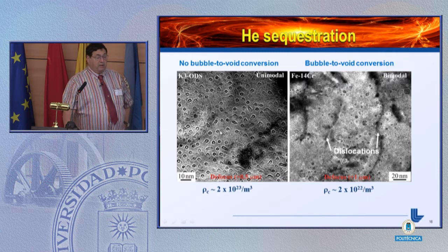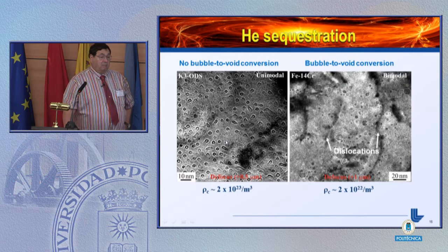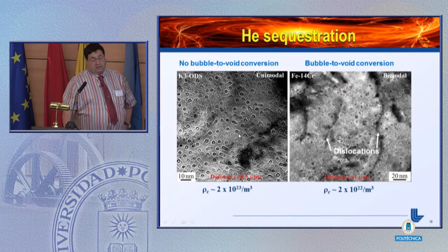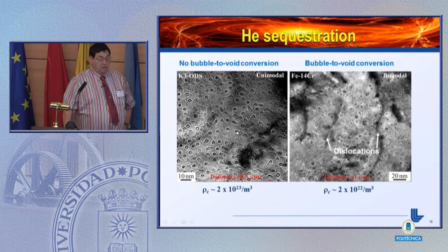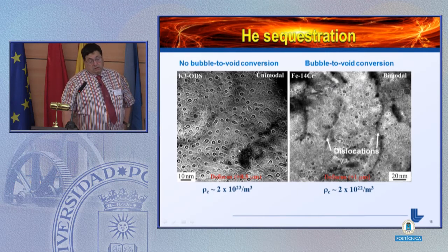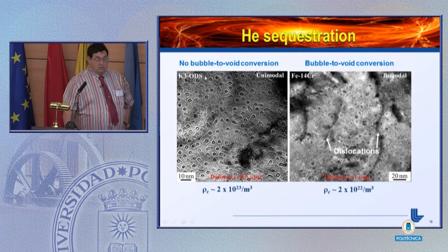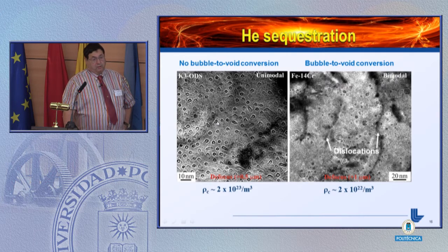cavity growth model in the presence of helium. These models were developed in the 1980s by a number of people, but the analyses that we have done are primarily based on the work of Mansur at Oak Ridge. And what you're seeing here is that in the case of the K3 ODS material, the helium has resulted in forming small, what we call bubbles.